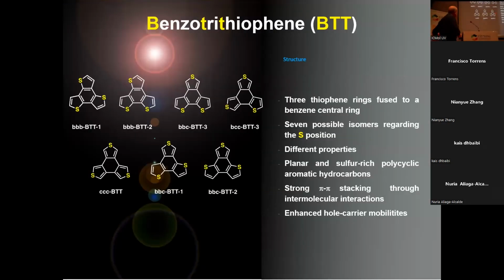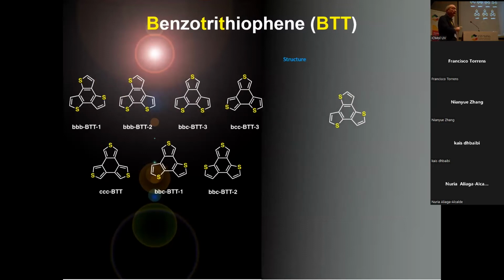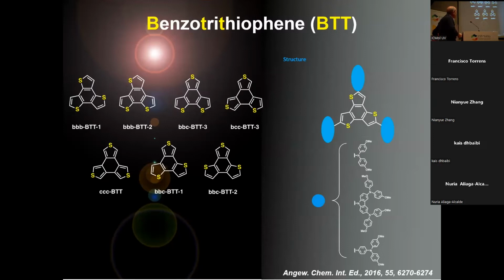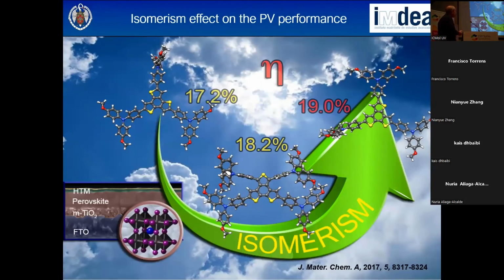And just very briefly, the BTT, the benzotrithiophene, there are 7 in principle. You could expect 7 molecules, of course, with different properties. All of them have in common that they are planar, with strong pi-pi stacking interactions. This was the first molecule we started to work with. And we used the arylamino as electron donor moieties, but also the carbazole unit having the TPAs, and this is the triphenylamine as well. We published this paper, and you can see here the molecule we prepared. The efficiency came out a few years ago. At that time it was a really fantastic value, over 17%.